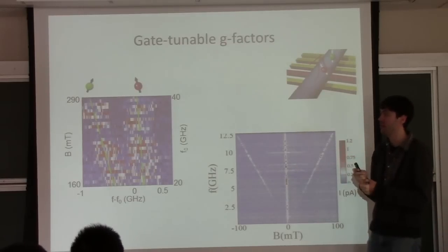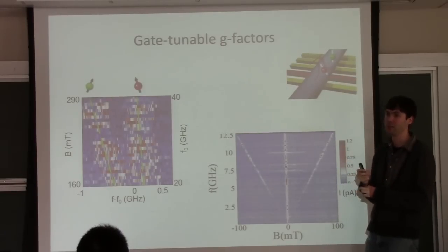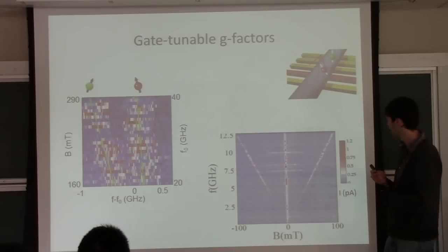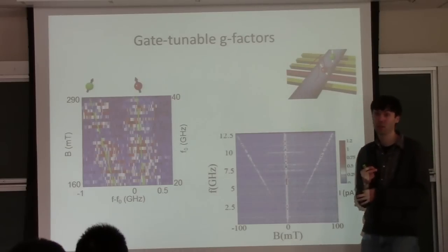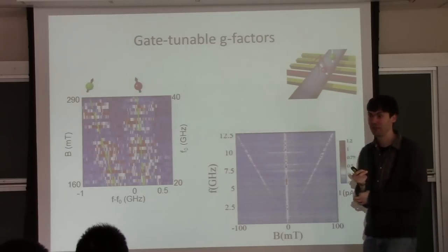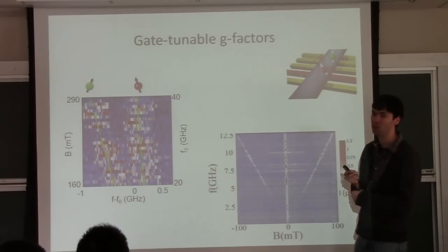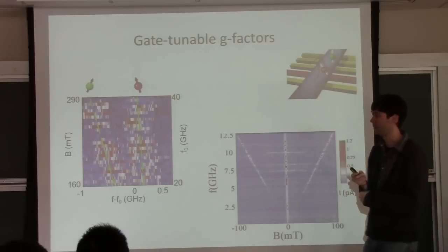They have slightly different G factors by about 0.3 in this material, in indium arsenide. So this is the entire G factor of gallium arsenide, which is 0.44. So in some sense, it's a large difference. But relatively speaking, it's something like 8.9 and 9.2. Those are the 2 G factors we found.